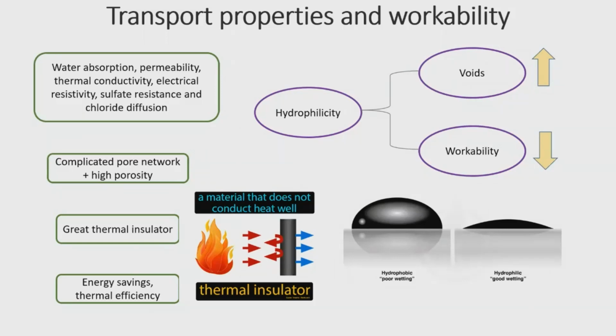In terms of durability of cementitious composites, a few important properties are electrical resistivity, sulfate resistance, and chloride diffusion. Free chloride ions are a major threat to reinforced concrete due to the depassivation effect, leading to corrosion and the formation of solids on the surface of the reinforcement. These volume increases derive in internal stresses and the eventual cracking of the concrete layer, thereby reducing its service time.